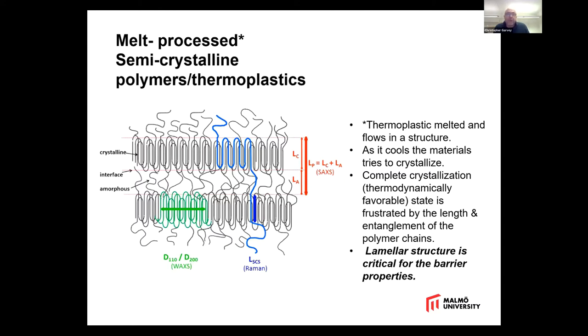But for our barrier materials, and also the tanks, which OmniTanker produce, the process is a melt, and it starts to crystallize and it can't crystallize completely. And what one is left with is this lamellar structure. This lamellar structure is extremely important for the barrier properties. So for example, if one has oxygen or moisture on the outside, it's difficult for the oxygen or moisture to diffuse through a film made of this material. So this lamellar structure is a layer of crystalline material and a layer of amorphous material, and a layer of crystalline material, and a layer of amorphous material.